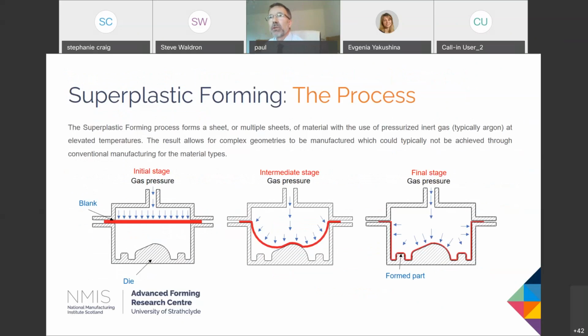So the process itself, what does it involve? Well, this is a nice little set of schematics which walks you through it. To carry out a superplastic forming operation, you obviously need to source your sheet in the first place, cut it to the appropriate size for the preform, and then the sheet is put into a press of a suitable type that has heating capability, and then clamped between the tools. And it's clamped so that it's gas tight, and then we actually form the sheet using gas pressure, and in this country we'd be using argon, to blow the sheet into the shape of the tool, as you see